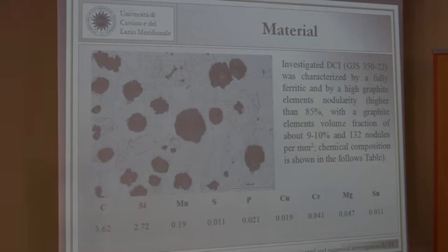We think we have evidence that the mechanical behavior of the external skin of nodules is different from the mechanical behavior of the core of nodules, because the phenomena that imply the construction of nodules are very different. In the first one we have the presence of diffusion in liquid phase. In the second we have diffusion in solid phase. It's different.